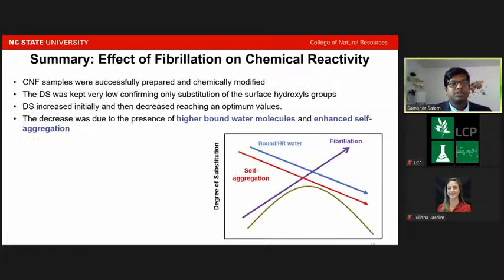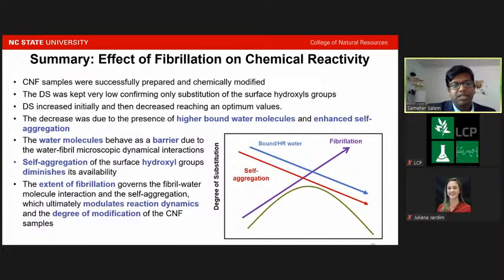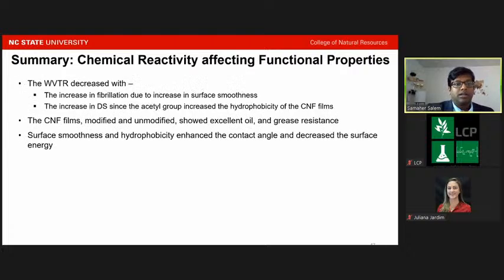So here is, to summarize all my work, we prepared the CNF samples successfully, and they were chemically modified. And we could see that the three factors, the bound water or hard to remove water, which forms the hydration shell, the fibrillation and the self-aggregation, affect the extent of reactivity of the nanocellulose samples. We also measured how the chemical reactivity affects the functional properties.